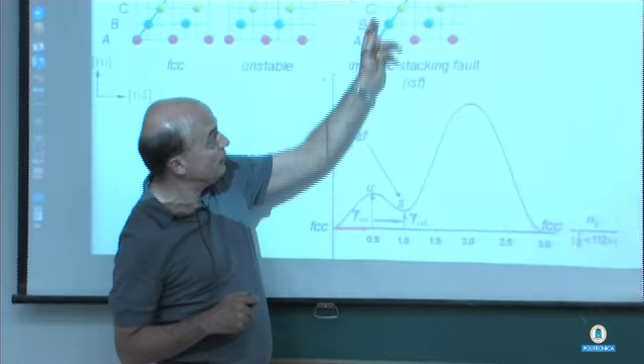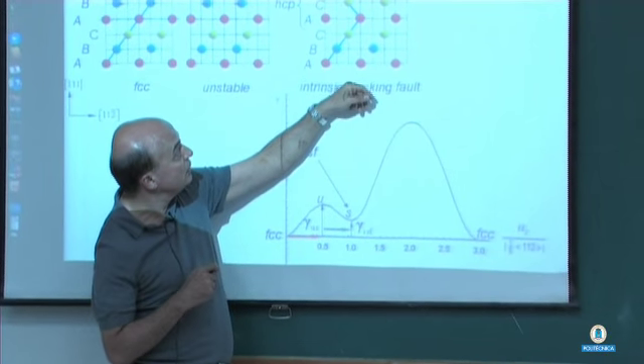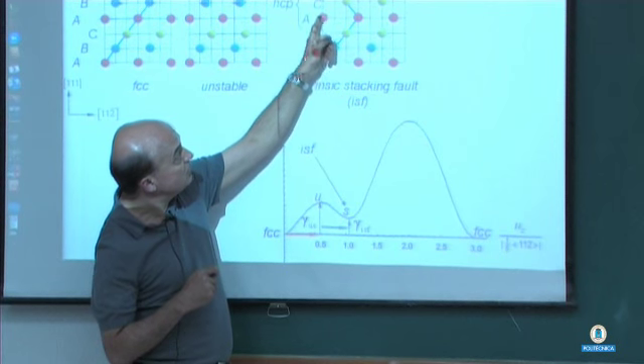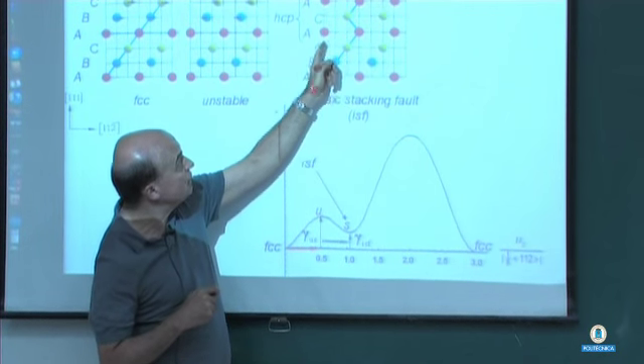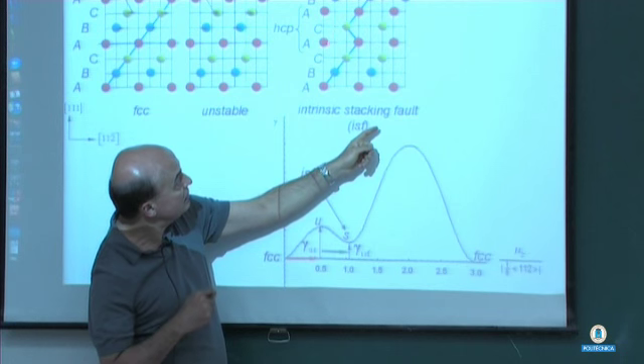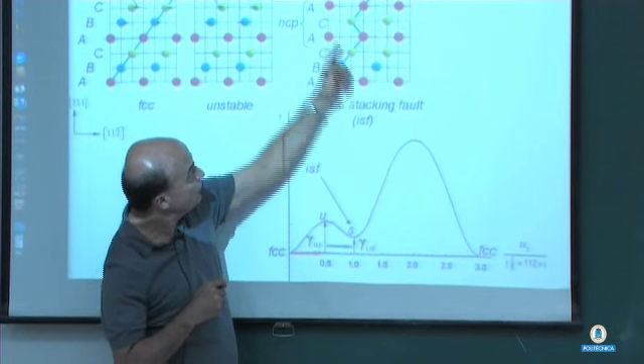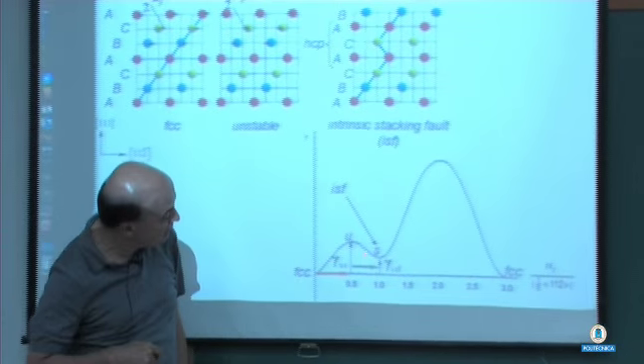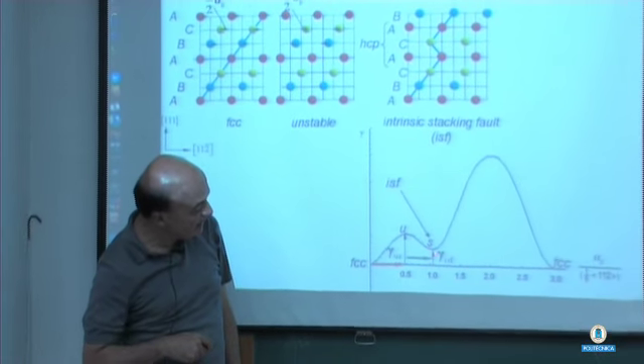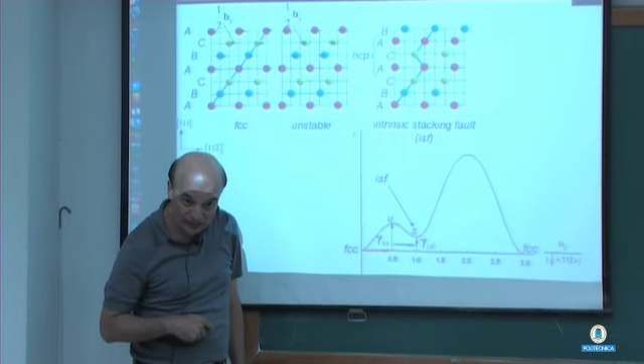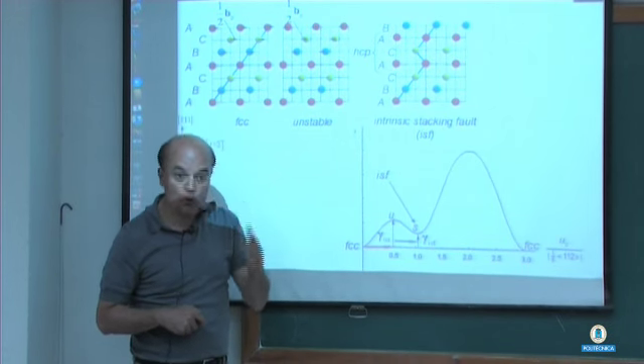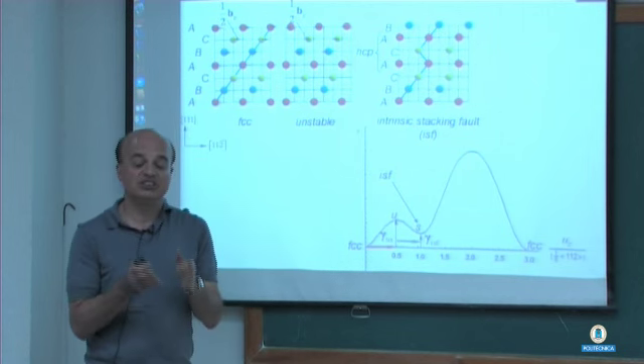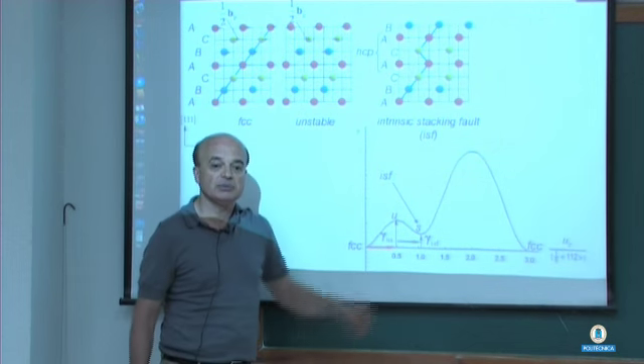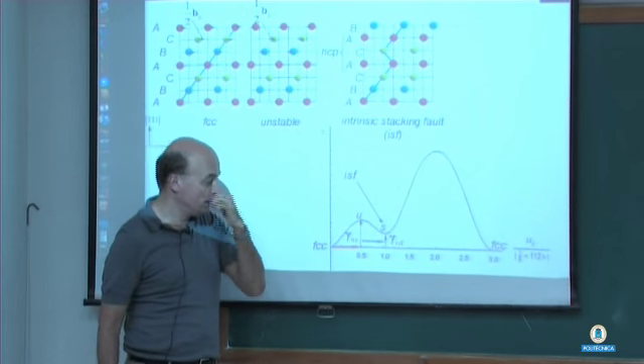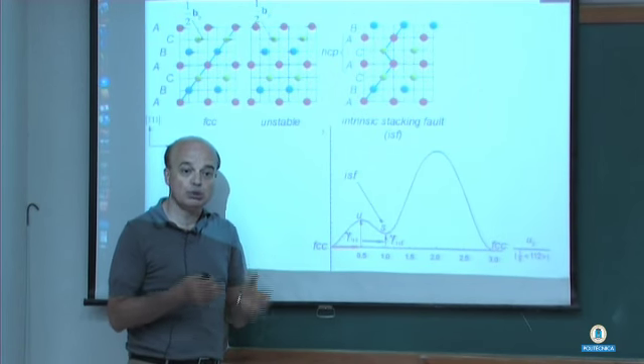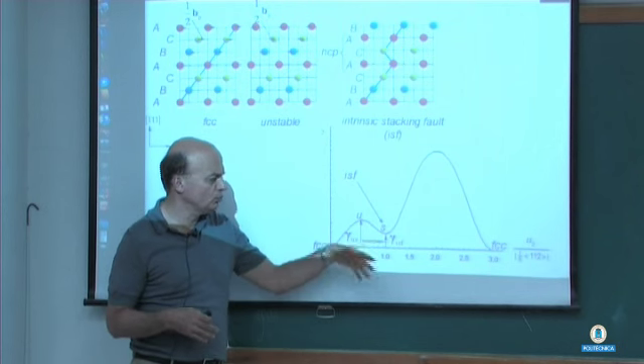So this is the ABC stacking of the face-centered cubic material. So here, this is a one-layer fault, because you get AC, and then from then on you get again ABC stacking. In that position you are in S, and the energy associated with that metastable position is called the intrinsic stacking fault energy. This is available in textbooks. It has been measured, and even elementary dislocation books quote you values for these things.